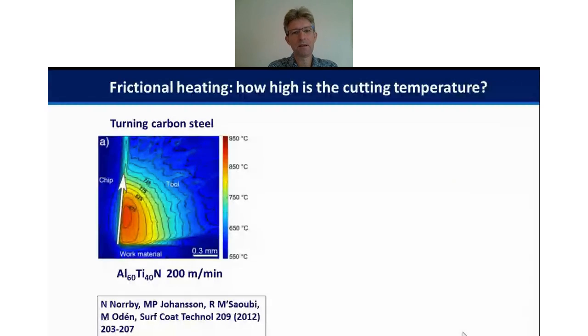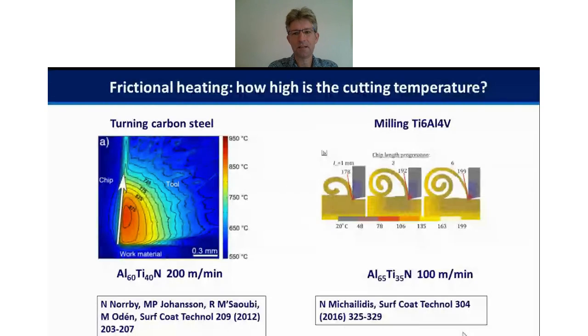So if we think about one particular high temperature application, that is high speed metal cutting, and friction is generated during the high speed cutting. So the question might be, what sort of temperatures do you reach? If you do a continuous turning operation on a carbon steel, as in this piece of work here, a thermal image from Linköping, you can see that you achieve very high temperatures, around 900 degrees, right near the cutting edge. If you have a discontinuous cutting operation, in this case milling of a titanium 6-4 alloy, then you can see the temperatures are rather lower, but they're nevertheless very much higher than room temperature testing.